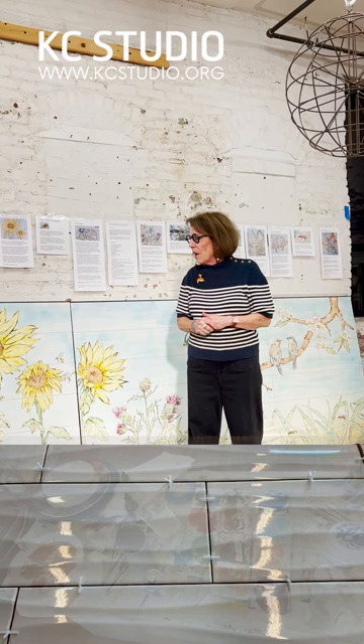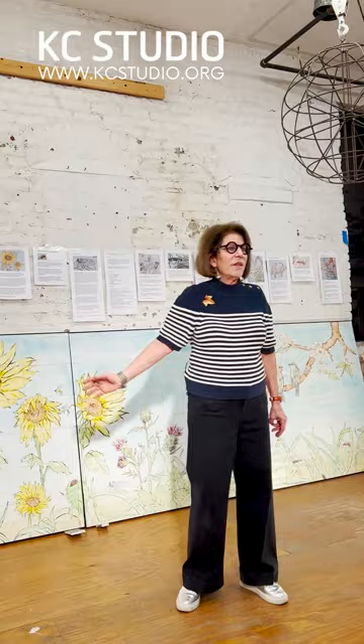I do a lot of china painting, so that's what this is. I bought the tiles — I think they're Portuguese — and they were really well behaved, because a lot of times china paint is really translucent and needs a couple of coats to come up so you can see the color. So a lot of these tiles have been fired five times. In the kiln, things expand and contract, so tiles are especially tricky. Then one other problem: since there's a war in Ukraine, you couldn't get mullite — that's what you use to set the tiles standing up in the kiln.